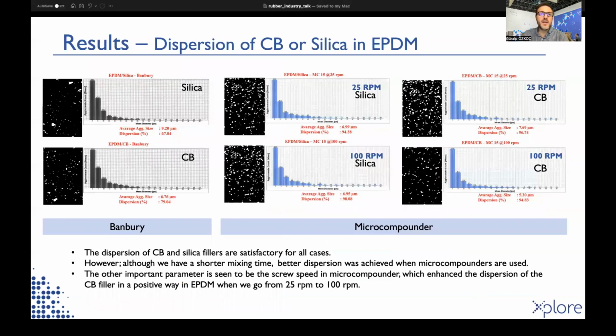Now, let us look at the dispersion of compounds prepared in different mixers. You can see from the dispergrader images that the dispersion of both carbon black and silica fillers is satisfactory for all cases. Generally, the dispersion of carbon black and silica in a polymer matrix is related to reducing the size of carbon black or silica in the form of aggregates.